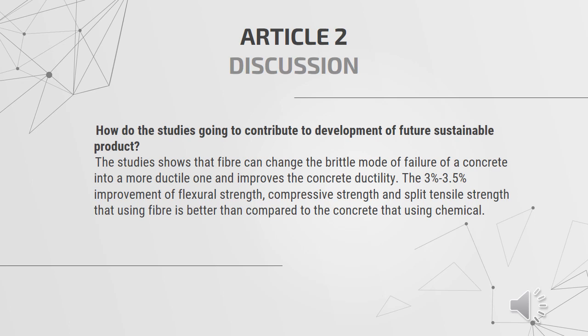How do the studies contribute to the development of future sustainable products? The study shows that the fiber can change the brittle failure of concrete into a more ductile one and improves the concrete ductility. The 3% to 3.5% improvement of flexural strength, compressive strength, and split tensile strength using fiber is better compared to the concrete that uses chemicals.